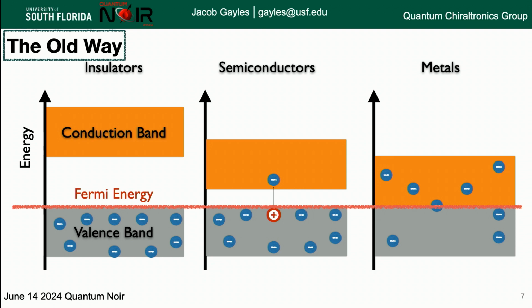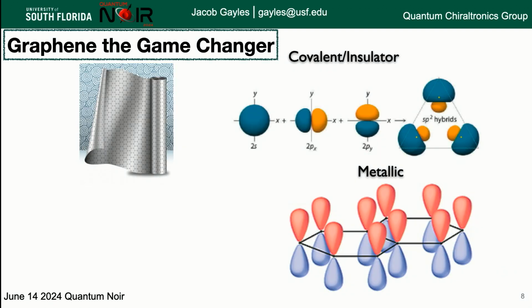And in this case, the gap is very large and it's almost impossible to excite electrons to that next level. Good. So the theory for this was done a while ago, but graphene came and changed the game drastically. And one case is not only did you have to use physics to understand these materials, you have to use also chemistry. So what graphene has is these carbon atoms, which are made of S and P electrons. And so the S electrons and the PX and PY, they hybridize and they form this covalent insulator type bond. So no longer do I just have purely an insulator or purely a metal, I have some mixture of it.